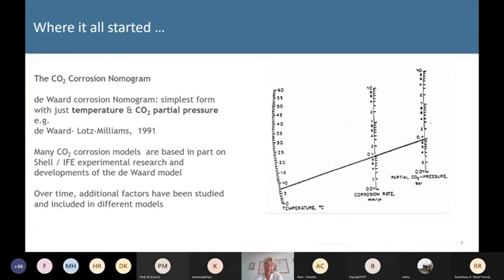In the early 1980s, I began work with Shell in 1981, and he was at the time working with me in the Netherlands, and we had the problem of CO2 corrosion arising in what was called the Groningen gas field, the largest gas field in Europe. It had about 0.7 bar of CO2, and at the typical temperatures of 40 to 50 in the field, we were getting corrosion rates of about 0.7 millimeters a year. You can see that if you move this line on this nomogram and link up 0.7 and about 50 degrees, you'd go through around 0.7 on the corrosion rate chart.